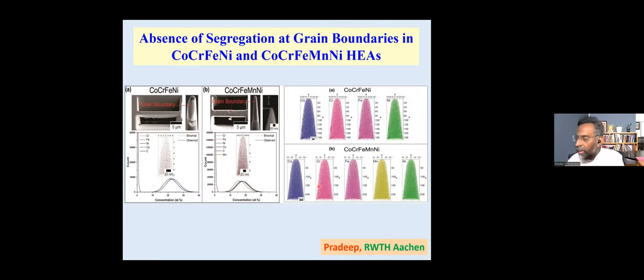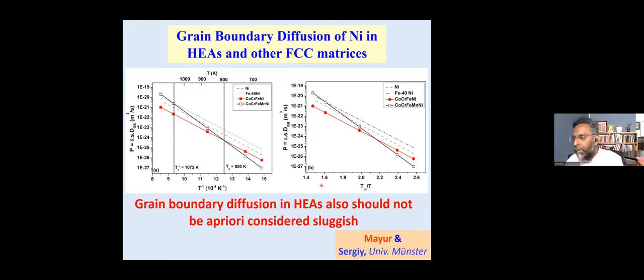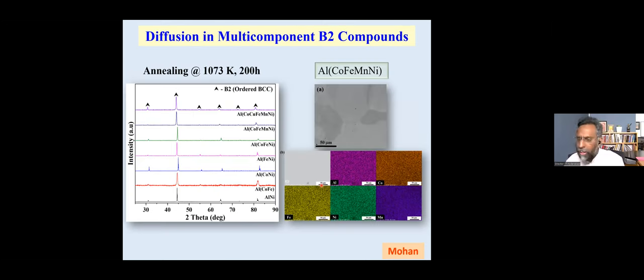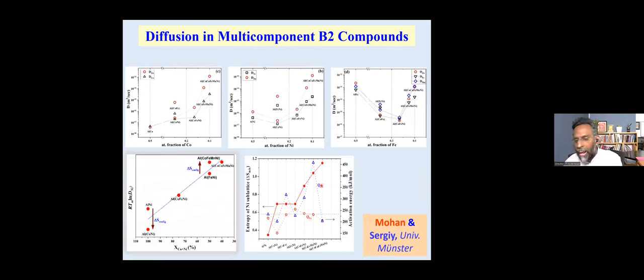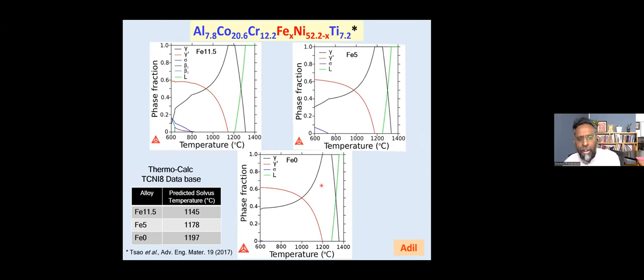And then we also wanted to see whether there is a grain boundary diffusivity, whether it is different from the bulk diffusion. We did some studies to even find out whether there is any grain boundary segregation in these materials. That also gave us an idea that there is absolutely no segregation even at the grain boundary in these materials. And some diffusion analysis has been done, which appears to be similar to what we get from bulk diffusion studies. We did this on a number of alloys. These are certain compounds where we have done diffusion studies and a lot of interesting data that we have obtained. So I'll not go into the details of this and tell you that it is possible to do that.